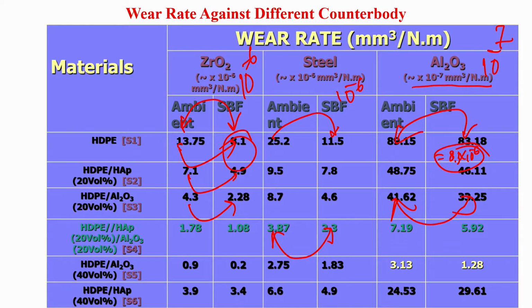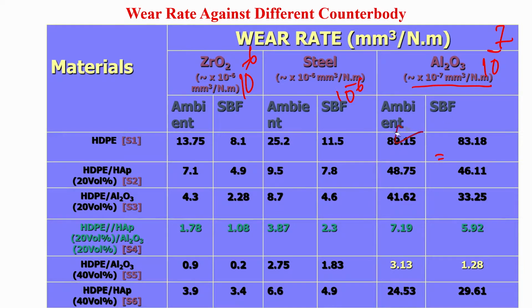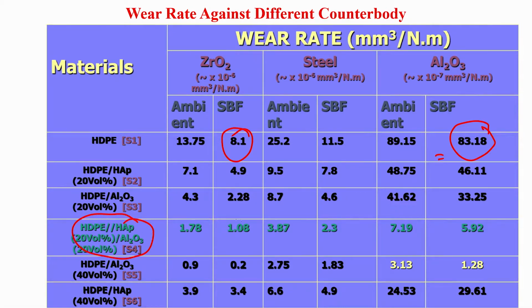Now if you look at the SBF results alone, what you notice here is that in case of HDP it is 8.1 into 10 to the minus 6, and here it is 83 into 10 to the minus 7, which is almost comparable. However, if you look at HDP HAP alumina, it is 1.1 into 10 to the minus 6, and here it is 5.92 into 10 to the minus 7.